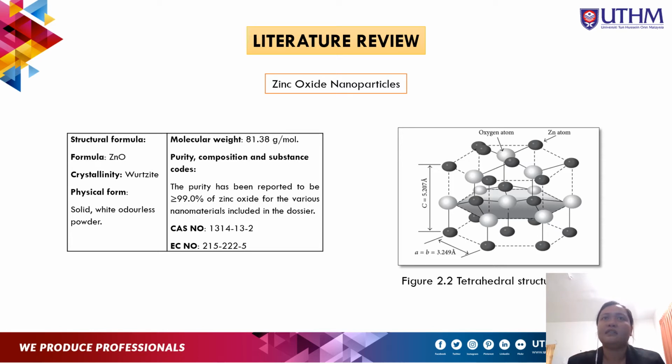The crystalline has the wurtzite crystal structure, having a hexagonal unit cell with 2 lattice parameters, and in this wurtzite hexagonal structure, each anion is surrounded by 4 cations at the corners of the tetrahedron, which shows the tetrahedral coordination and hence exhibits covalent bonding. The tetrahedral configuration of zinc oxide gives rise to a non-centrosymmetric structure as shown in the figure.